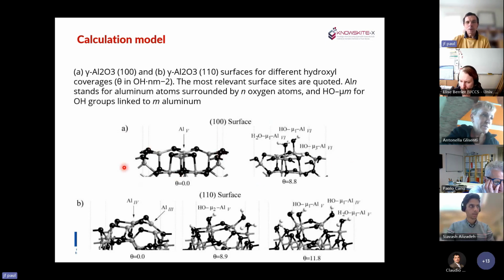So if we start from alumina, we have here the example of a 100 surface of the gamma alumina, and you can adsorb quite a lot of OH groups on top of it. And the first, second surfaces are quite the same, and the number of OH that you will adsorb on the surface will depend on the temperature.